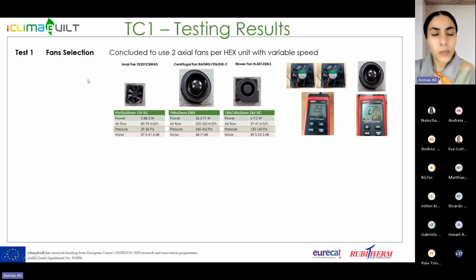So the first test was to select the best fan. We chose one of 3 fans: starting with a low performance axial fan, but less noisy; a high performing centrifugal fan, but very noisy; and a middle one, a blower fan, with middle performance in both acoustic and power performance. After many tests, we concluded that 2 axial fans are comparable to the centrifugal fan with high performance, and we will use 2 axial fans in series, and this will also help in decreasing the dimensions of the upper box.